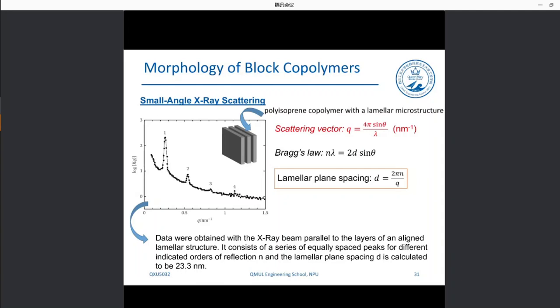The advantage of small angle X-ray scattering is that it provides information from the whole of the sample. And if we look at this example, it's called SAXS. Where we have a polyisoprene copolymer with a lamellar microstructure, and we test the sample through small angle X-ray scattering, we obtain this plot where we have the scattering intensity, and here we have the scattering vector.